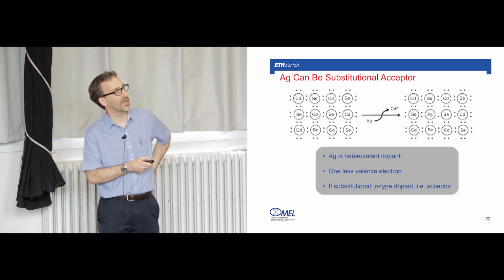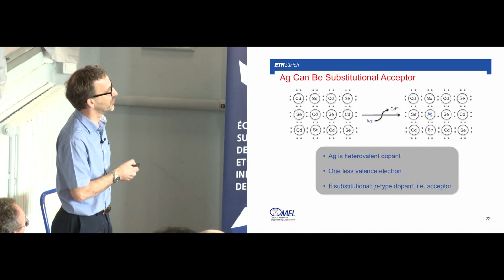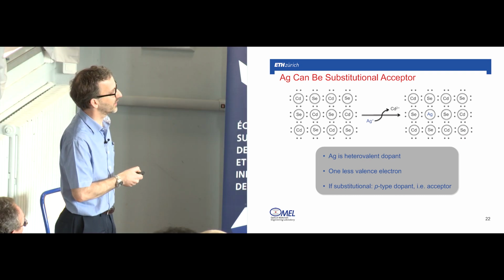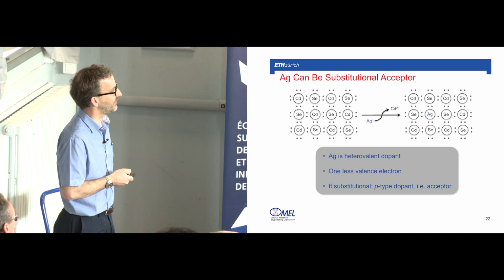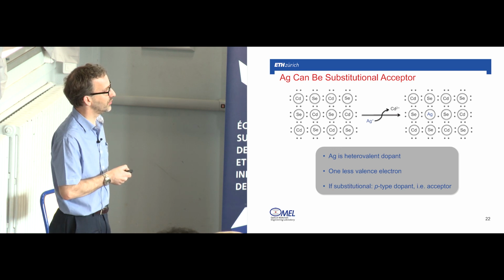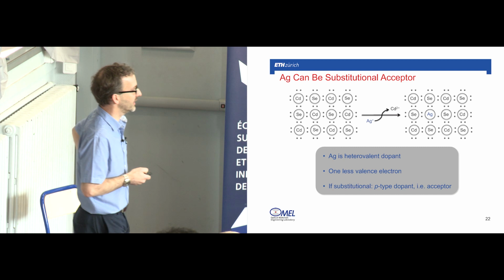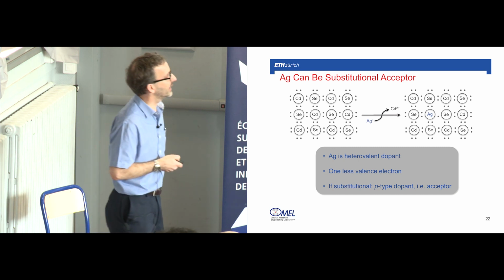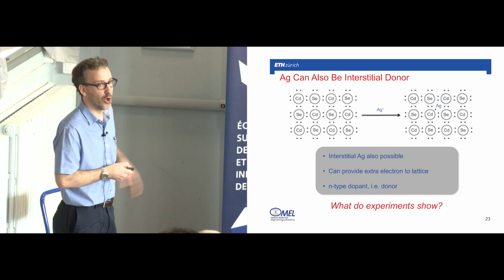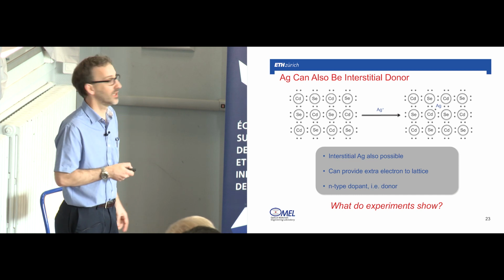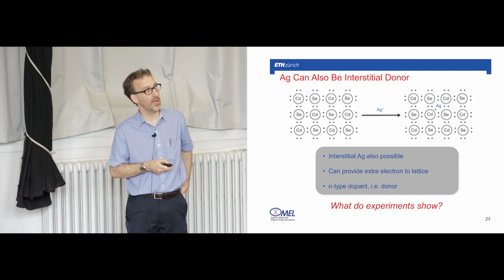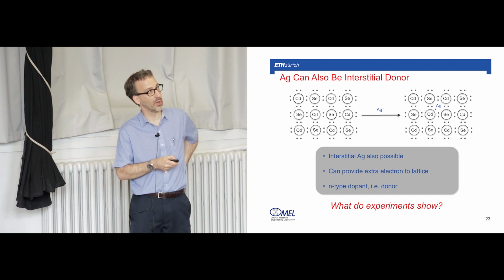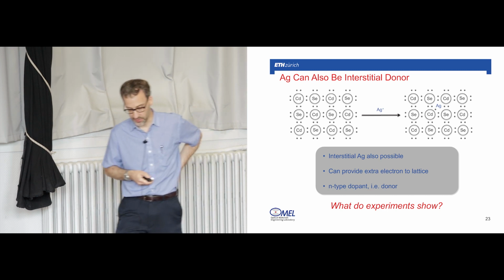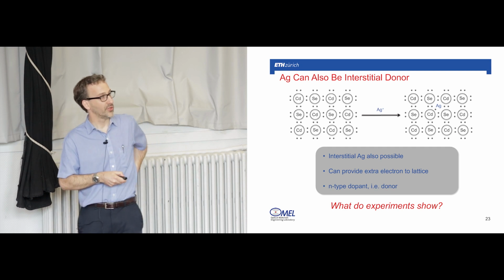Now, what would we expect from silver? Silver could be a substitutional acceptor. If it swaps out for cadmium, it has one less valence electron, and so it could introduce a hole and be p-type. Or it could be interstitial. It's known to be a fast diffuser in cadmium selenide, so it could be diffusing through the interstitial sites, and then it would be a donor where it would give its extra electron to the lattice. So what do the experiments show?